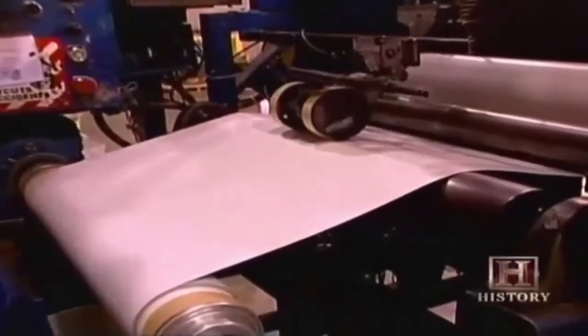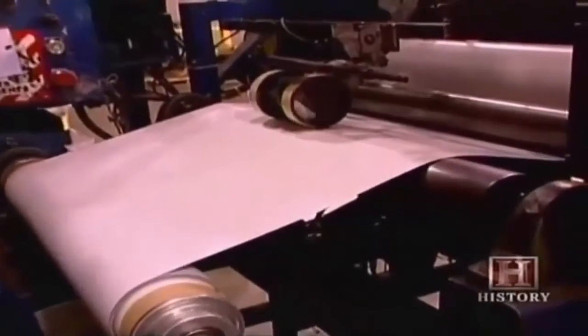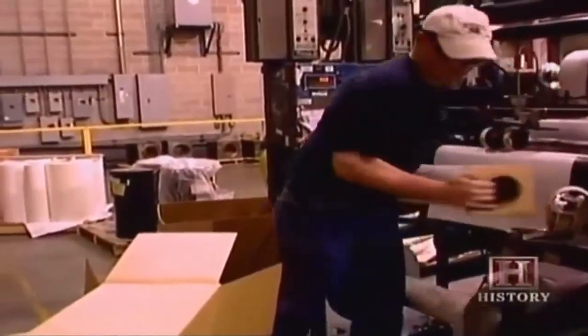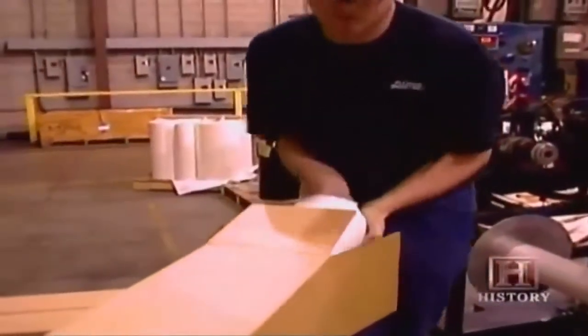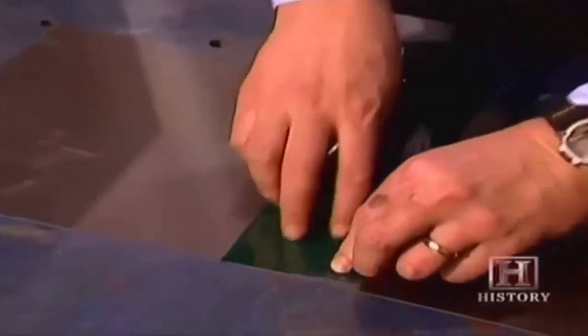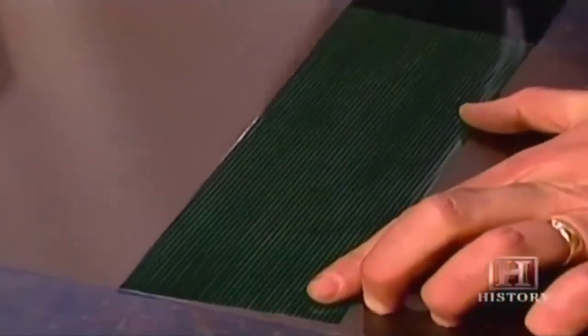But before FlexMag ships the rolls to its clients who apply those touches, how can it be sure of its product's stick-to-itiveness? One of the ways we make sure that the magnetic material is actually magnetized is we use sheet vellum. The vellum is actually two thin pieces of plastic with a liquid medium in between that holds fine magnetic particles that align with the magnetic pattern. And this material will show you the magnetic imprint on the magnetic sheet. As you can see, it's the same magnetic imprint that we used on the rare earth magnet roller.